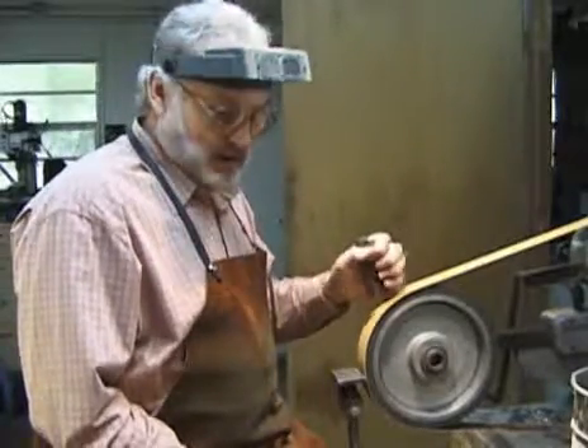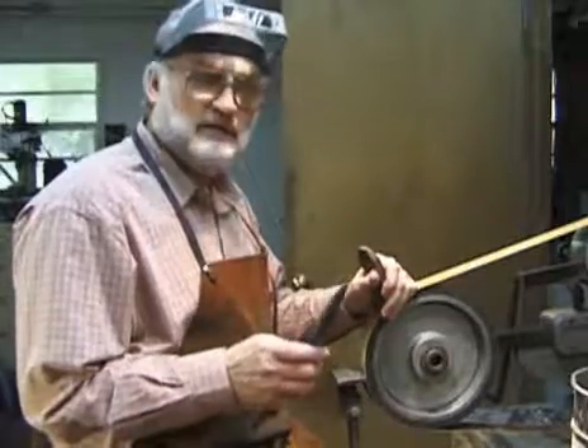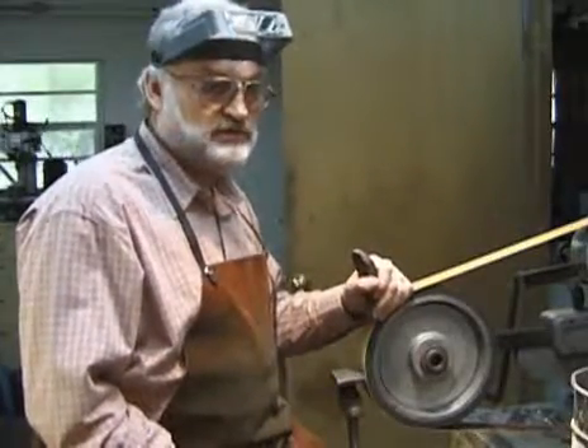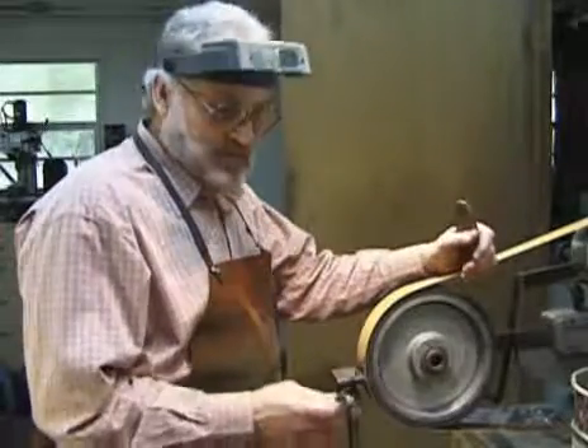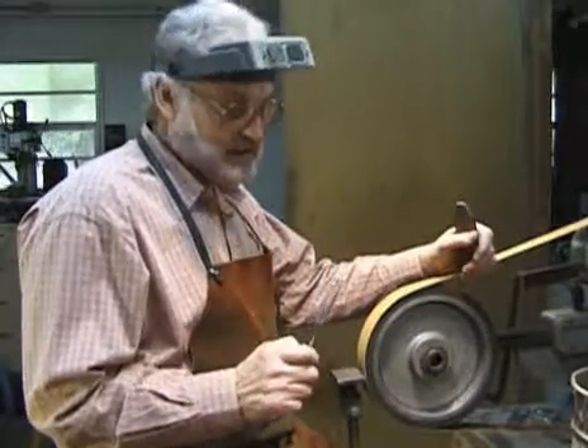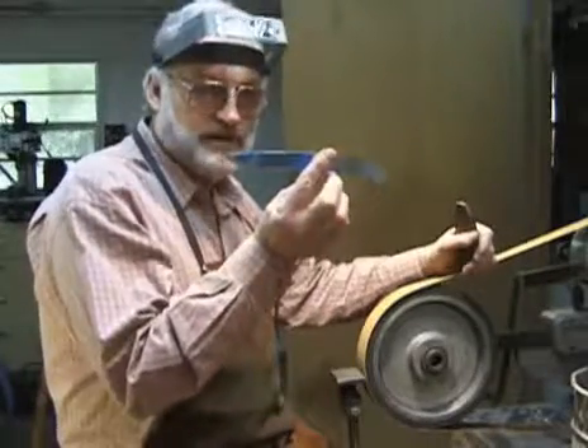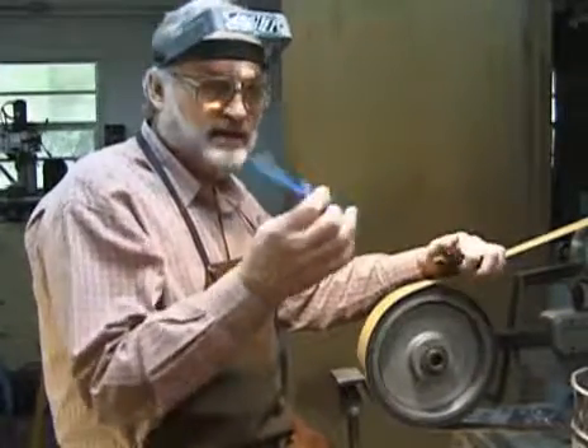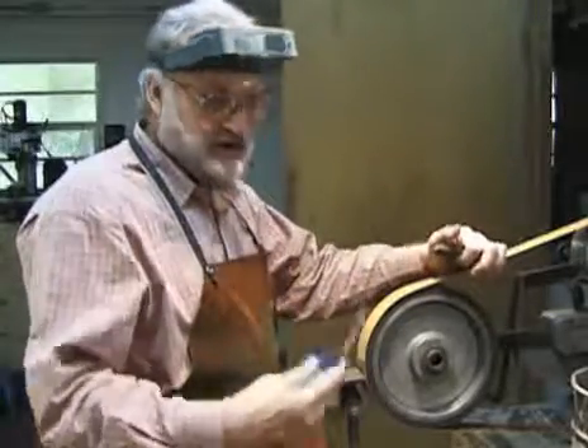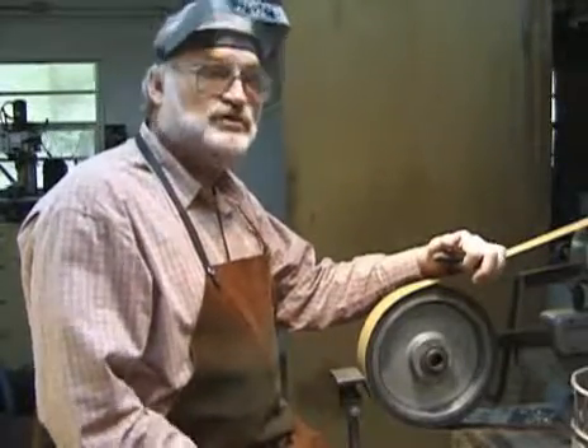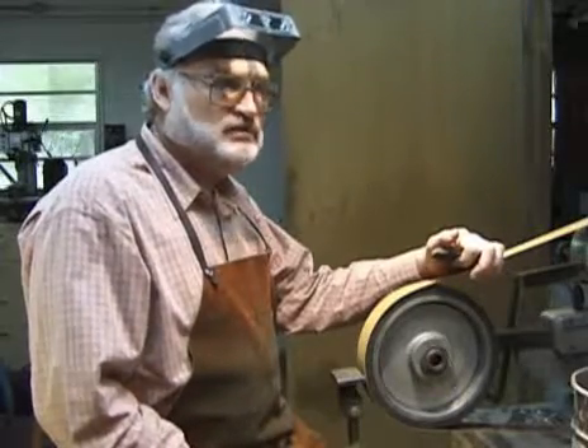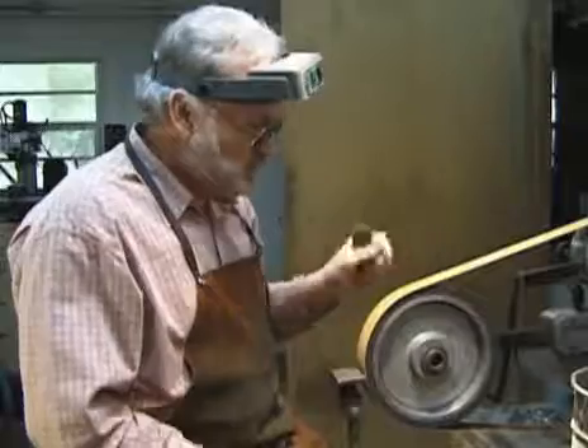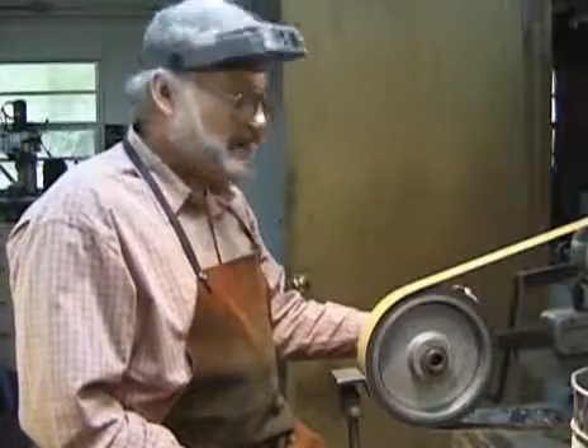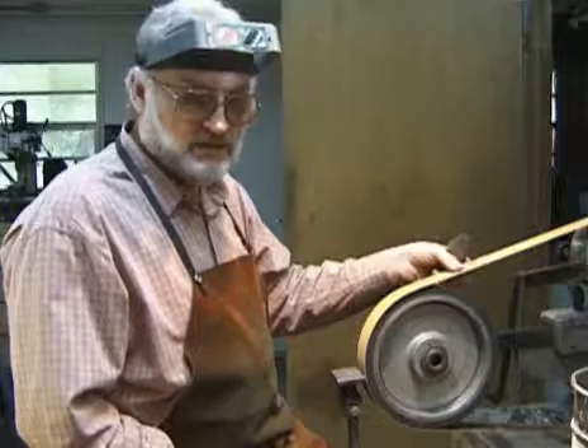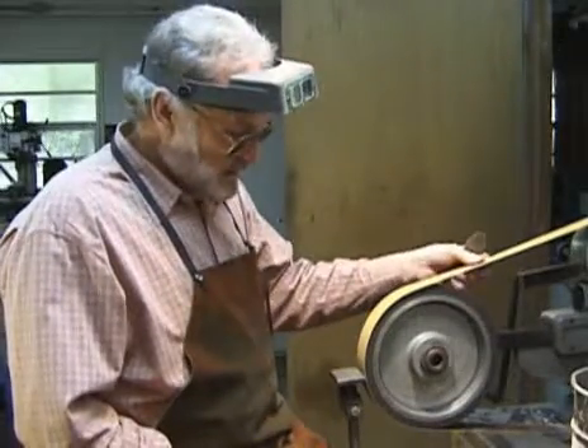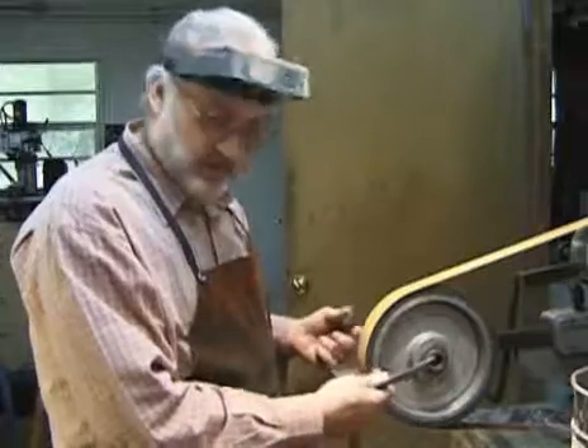So if you're doing small blades, be careful about using really, really aggressive grits because they're hard to get out. So even on my smaller blades, I'll normally use an 80 grit, and this is about an average size blade for the knives that I make. But the larger your knife, the coarser the grits you can obviously use, because you've got a lot more material there to take off. But the point I want to make is that when you get into your finer and finer grits, the thickness of this belt gets a lot thinner. And what happens, the radius of your wheel actually changes.